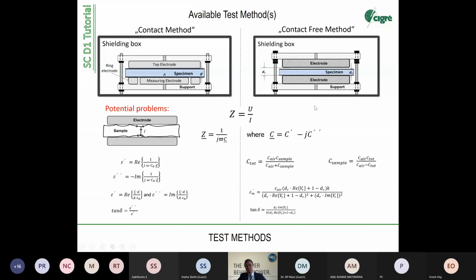The right one is the contact-free method. And when you look at the samples or the arrangement, there is no guard ring. And you see a gap between the top electrode and the specimen, which is good, but is also part of a problem, because you have to calculate the air capacity and you have to calculate the sample capacity. At the end, you want to have the sample capacity, and from the sample capacity, you can derive tangent delta.